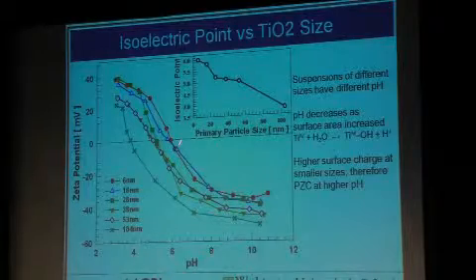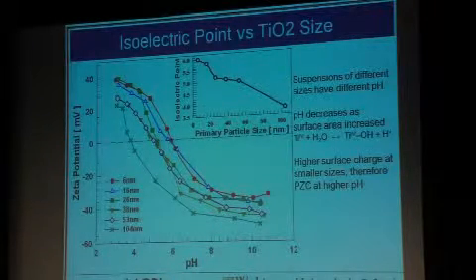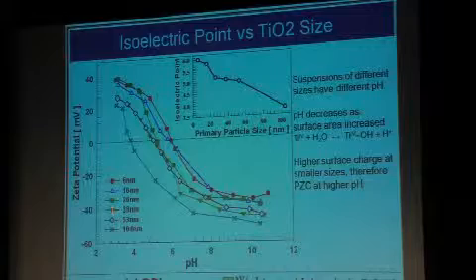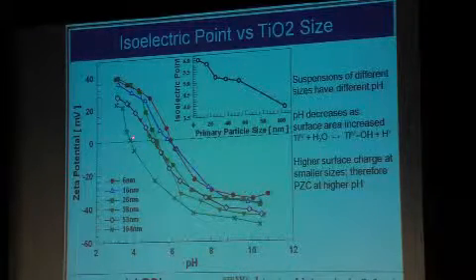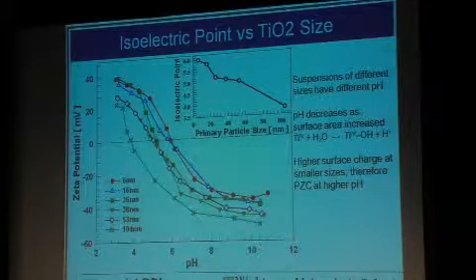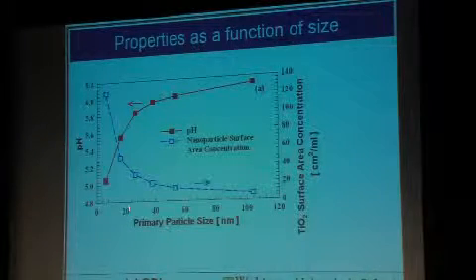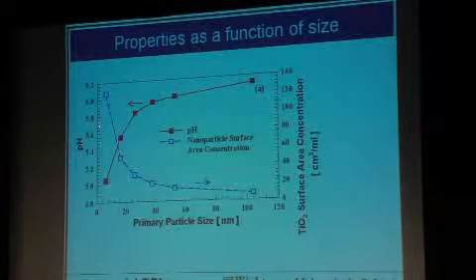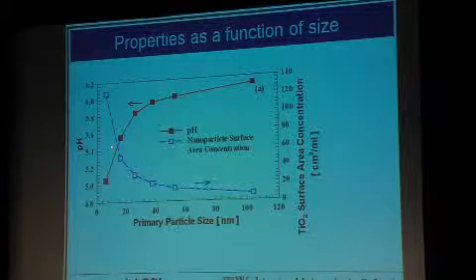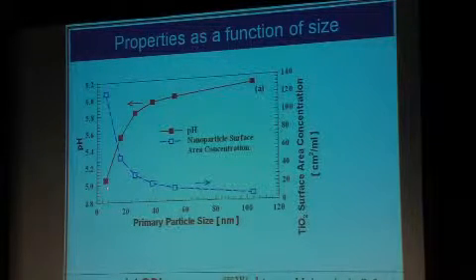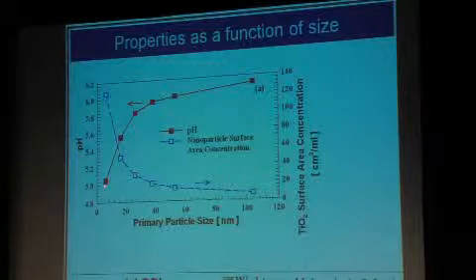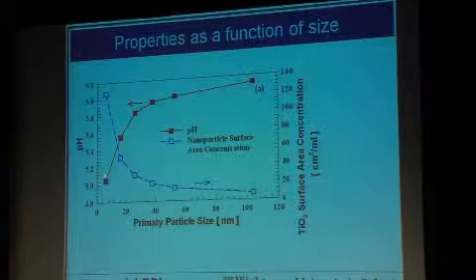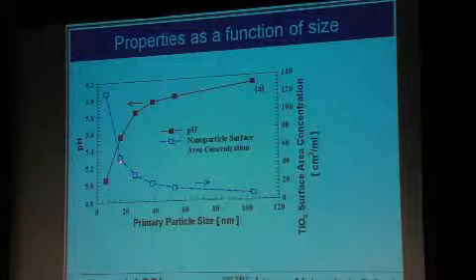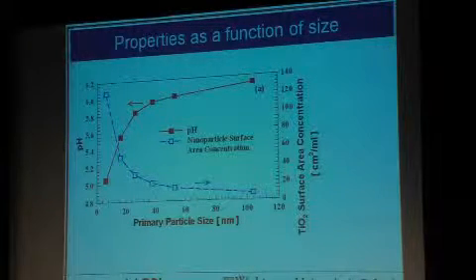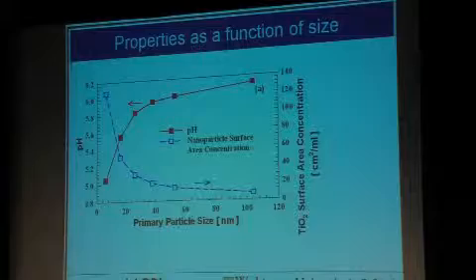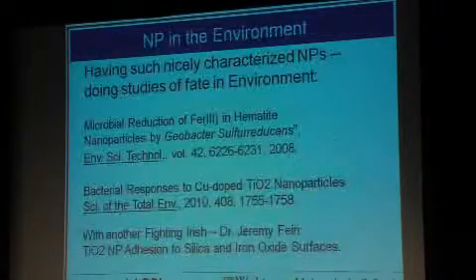So here is actual data now for all these samples. Only possible because we could make these materials very quickly, and you can see that the point of zero charge changes, and one can, of course, go through, and it all correlates to the total surface area now. So you can see as the surface area increases at low primary particle size, because of the large surface area, you're going to form more hydrogen ions, and the pH is low, and then the pH keeps increasing. So these are all very important, just a snapshot of some data that I wanted to show you.